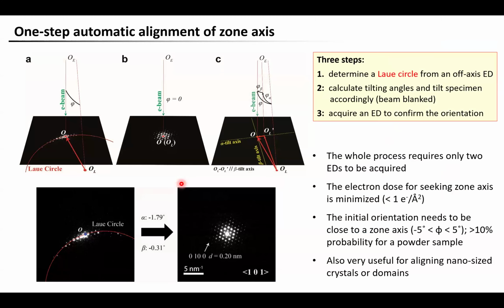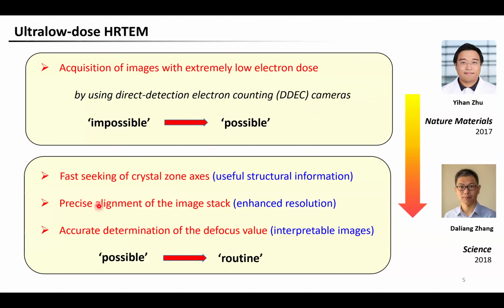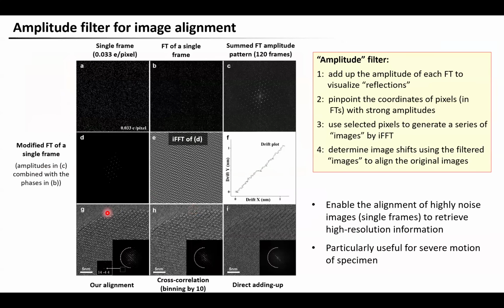So to solve this problem, we developed a method that enables one-step automatic zone axis alignment. So this method can effectively minimize the electron dose consumption for zone axis alignment, typically less than 1 electron per square angstrom. Well, the second challenge is how to precisely align the very noisy frames in the image stack. If we cannot do that, we cannot retrieve the high resolution information. But at ultra low dose conditions, the frames are highly noisy, so they cannot be precisely aligned using conventional methods based on feature matching or phase correlation. So to solve this problem, we developed a method that we call amplitude filter.